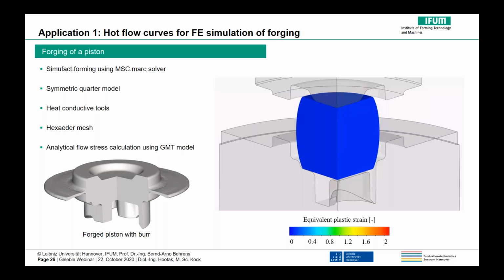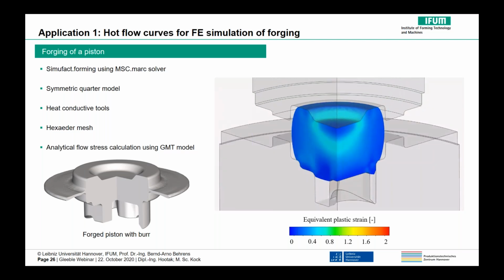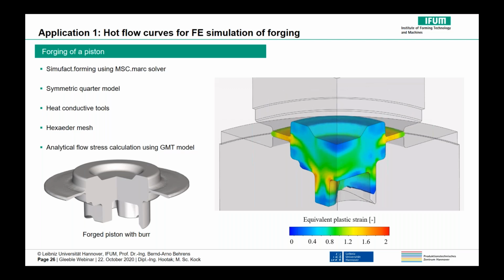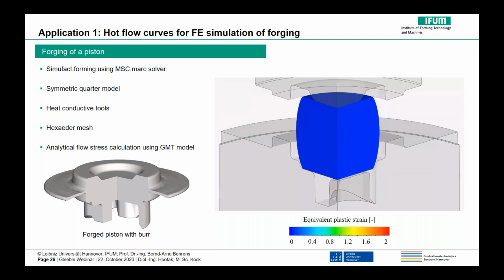The simulation is created with Simufact.forming and solved with the solver MSC Marc. The tools are modeled as thermally conductive rigid bodies. The workpiece is meshed with hexahedral finite elements, and the so-called GMT model is used to calculate yield stress. Thereby, the yield stress is calculated as a function of strain rate and temperature, by using an empirical equation. On the right side, we see the result of the forming simulation with regard to the resulting equivalent plastic strain. In order to carry out such a simulation close to reality, material characterization tests had to be carried out in advance.